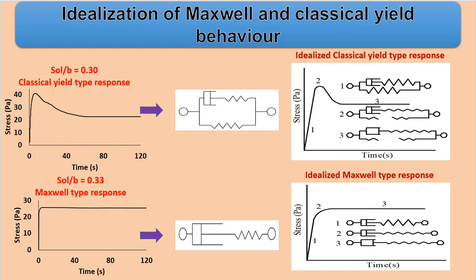What we found is that the paste, on subjecting to a constant strain rate, gives two distinct types of behaviors: classical yield type response and Maxwell type of response. A classical yield type of response is one where the paste on subjecting to constant strain reaches a peak stress value, there is a subsequent breakdown, and then it carries a comparatively lower load.